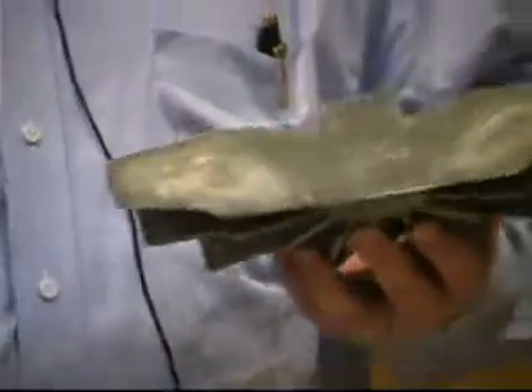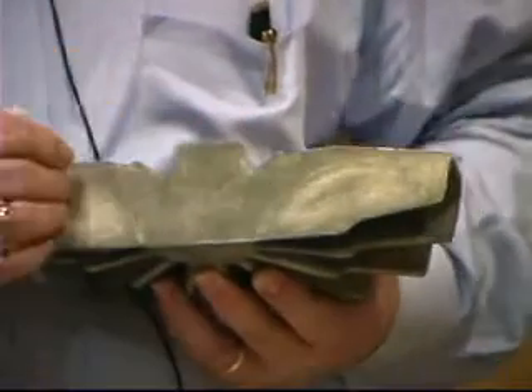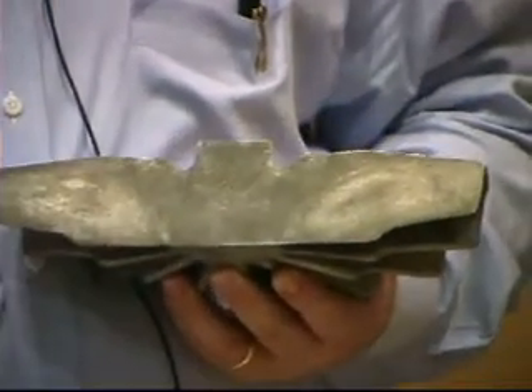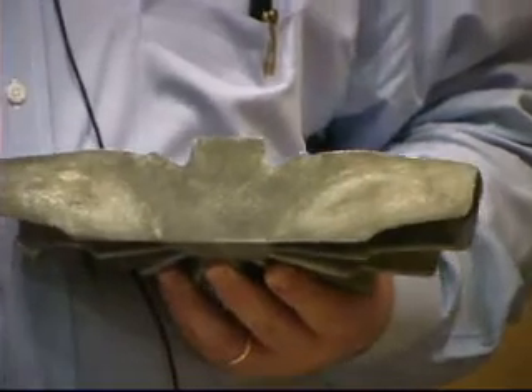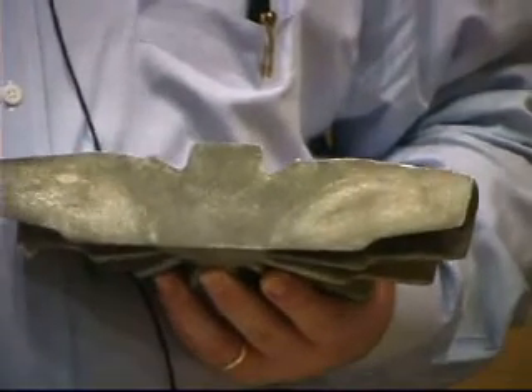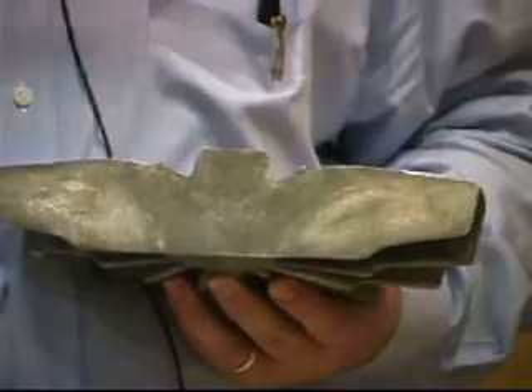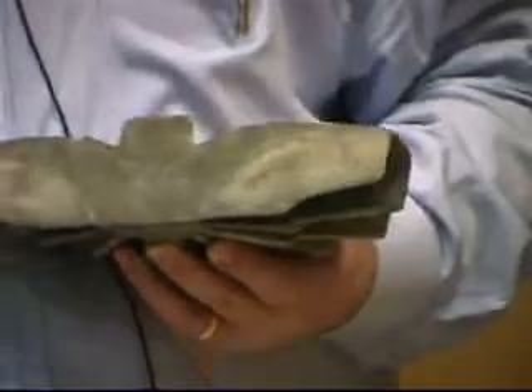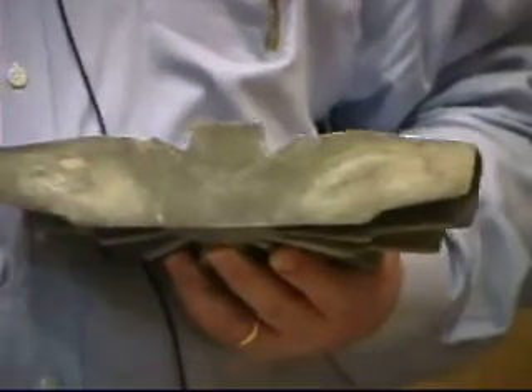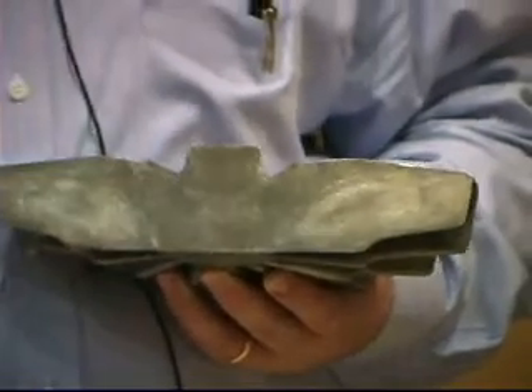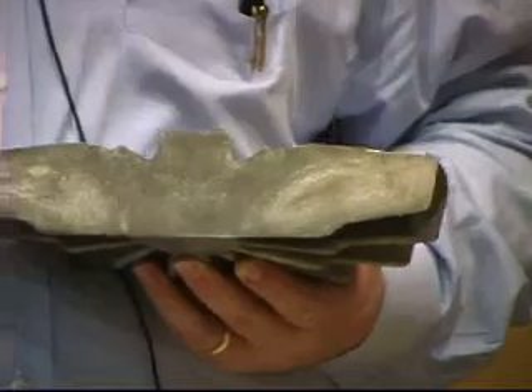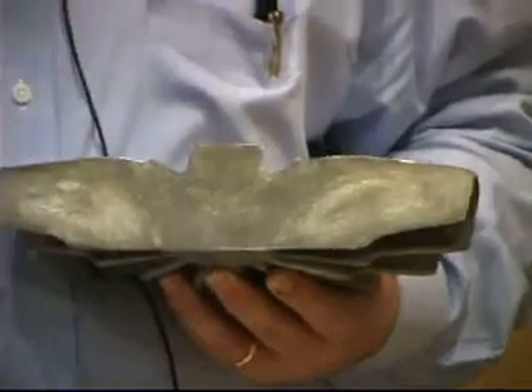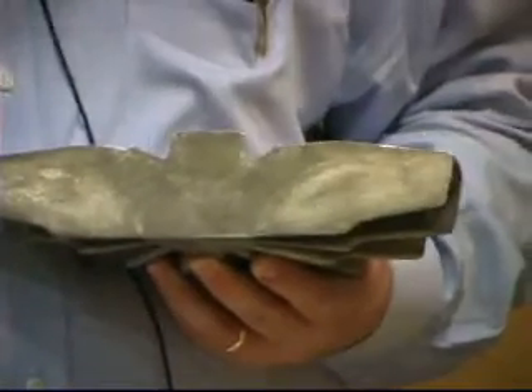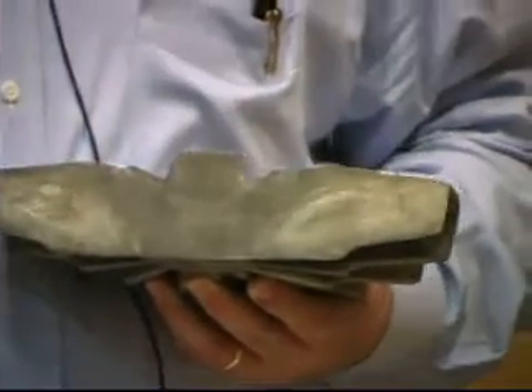I mean, the cast structure, I passed around that copper piece before, the continuous cast copper piece, and you can see the grain structure. But you want to actually break up that grain structure. In fact, that was the problem with that copper wire. The grain structure was too coarse, and it destroyed the properties. It made the surface bumpy, and when the train went down the track, the electrical contact, which is like 12,000 volts or something like that, would just go spark, spark, spark. It looked like the 4th of July as the carbon brush was sliding along this bumpy wire.